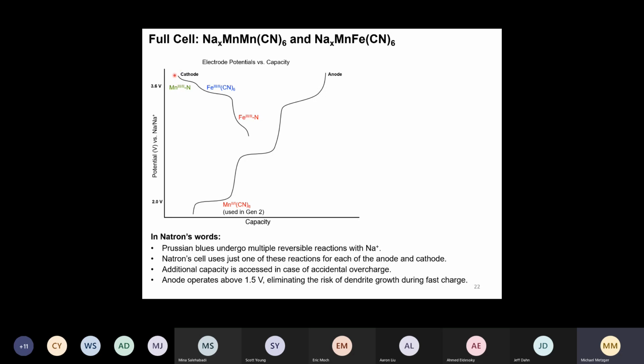So this is from last class, we saw that this material has basically 3 possible redox couples that you can access. So there's a high voltage redox couple, which is manganese 2+, 3+, which is coordinated to the nitrogen. That's this manganese here, so it can change its oxidation state between 2+ and 3+. Then there's kind of this intermediate voltage redox couple that they are using, so the iron 2+, 3+. And then you can also have manganese, which is coordinated to the carbon in the structure.